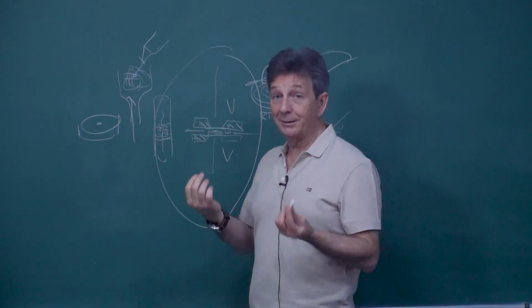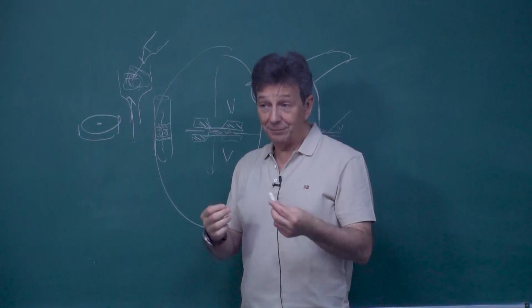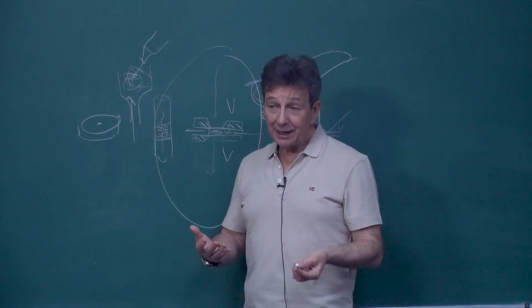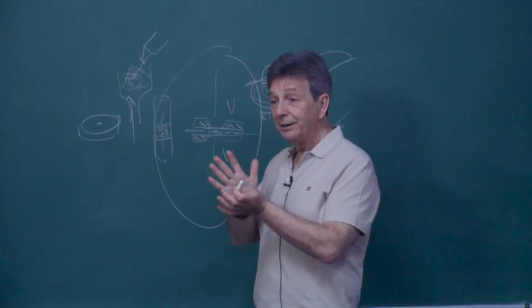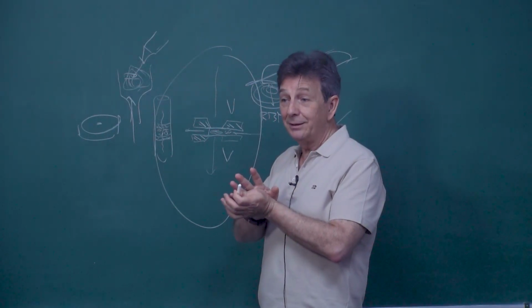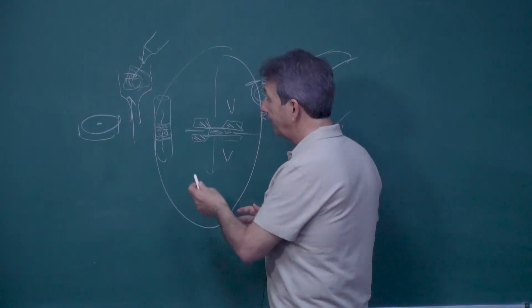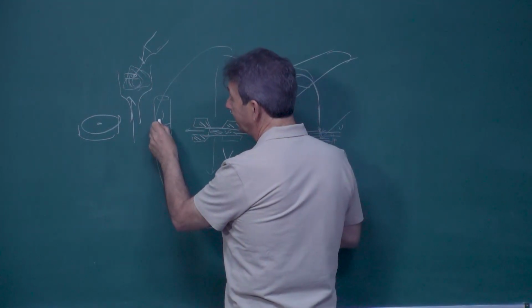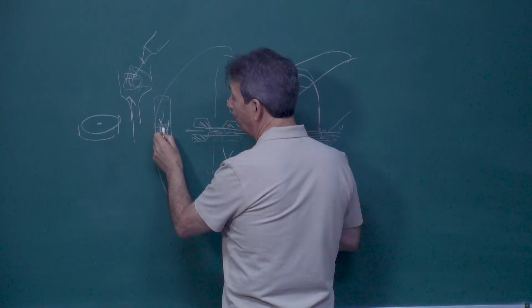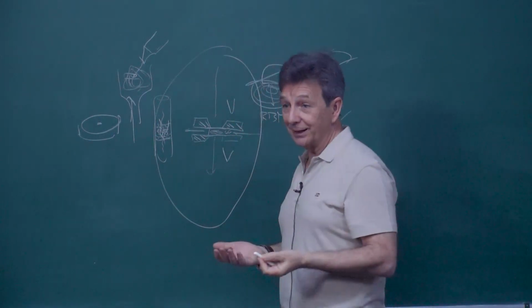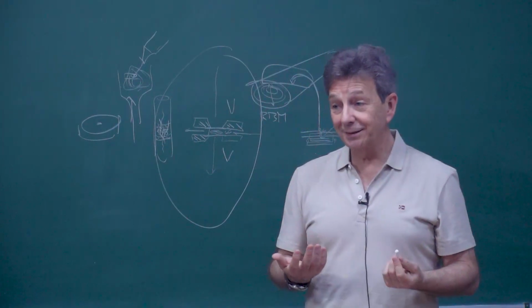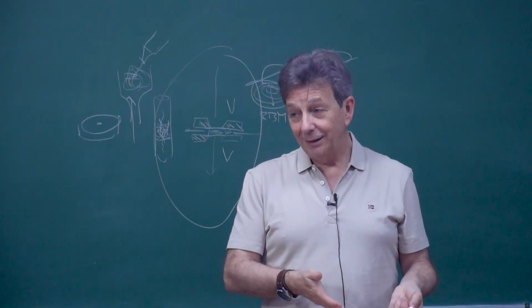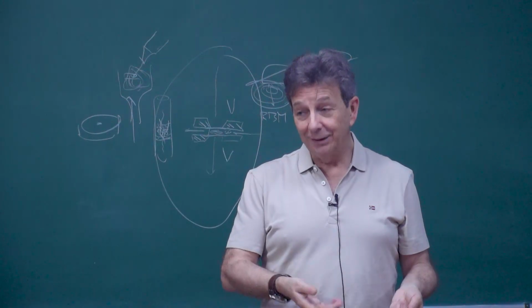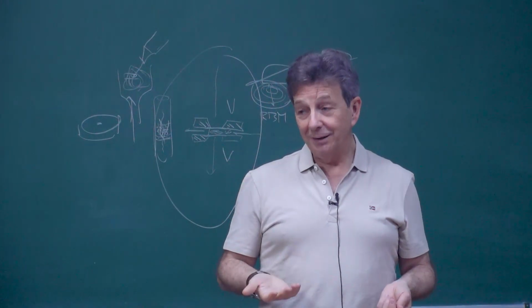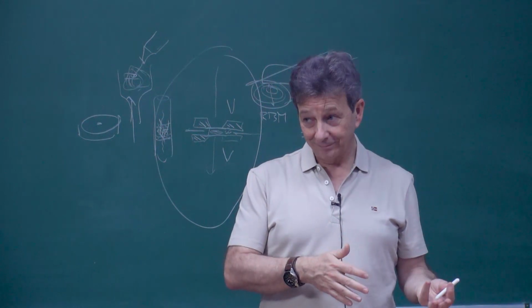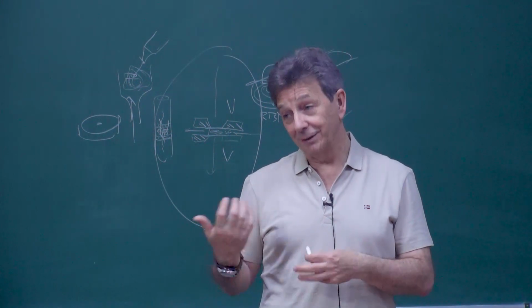Of course, if it's very small, they will plug it or they will flow away, but you never do a reaction with very fine powder, because in an industrial reactor with very fine powder, it will fly away. And if it doesn't fly away because you avoid it, it will plug, and there will be hardly any porosity, and then in the end the gases will only go through preferential channels, but most of the catalyst will not even interact with the gas. So usually you need a particle size that is not too small to avoid internal diffusion control, to avoid a problem of flying away, and to avoid many things. So nobody will have it very light that flies away. And it will not have it very big because there is another kind of diffusion.